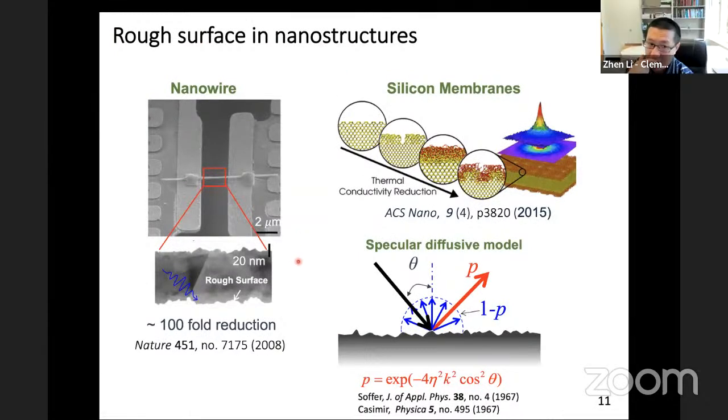So that means when you consider the nanowire thermal conductivity, you consider there's some roughness, there's a surface structure. This will help to generate high energy efficiency, right? If the thermal conductivity can be reduced in the nanowire, then the ZT factor for the thermoelectric energy conversion efficiency of the nanowire will be much larger than the bulk material.